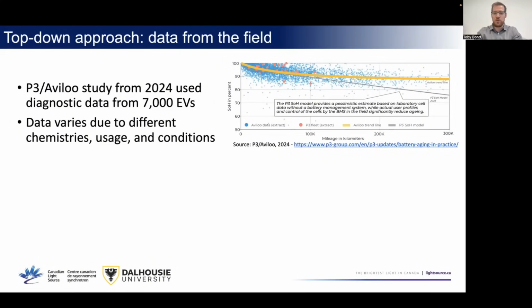So each one of these blue dots is a capacity measurement at a specific mileage. So it goes up to 300,000 kilometers on the right here, and you can see this average line for all that data does pretty much what I was showing you before. There's an initial faster kind of decay, but then it pretty much levels out. And at the end of that, the average is just under 90%, so doing very, very well.